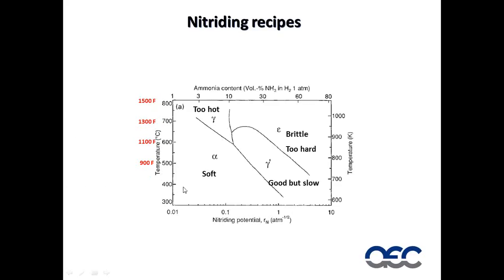So, if we operate around about 800 Fahrenheit with a low nitriding potential, we form a phase called alpha. It's just plain soft. We're wasting our time. If we nitride at the same gas potential, but at 1400 degrees Fahrenheit, it's too hot for the steel. The tempering temperature of H13 is around about 1000 degrees Fahrenheit, maybe 1100 degrees Fahrenheit. 1085, Paul is telling me, is the exact number. So if we go all the way up here to 1400, we're going to soften our steel.